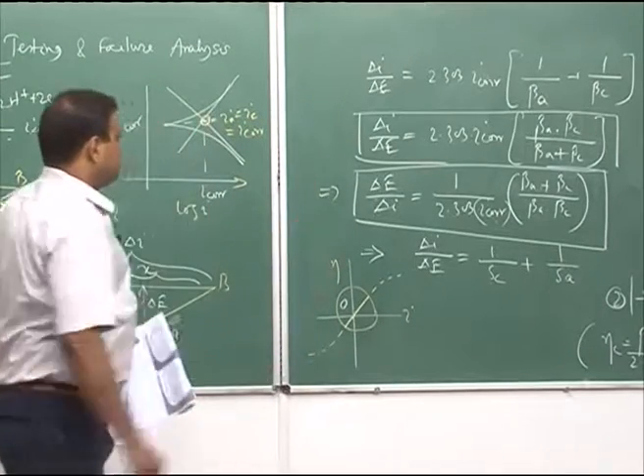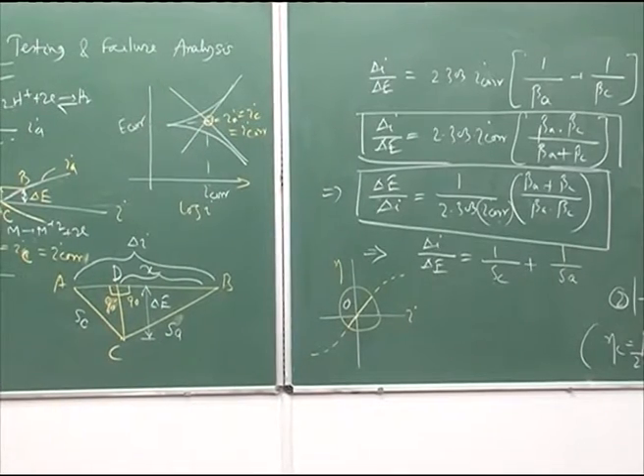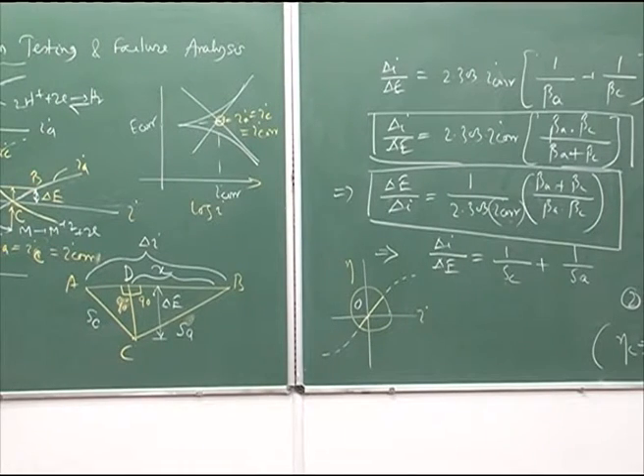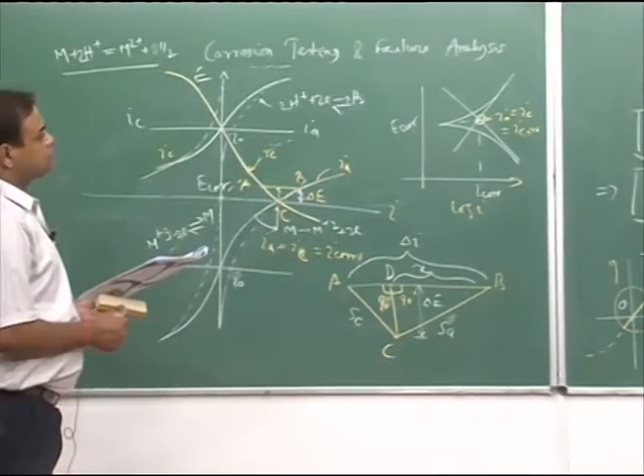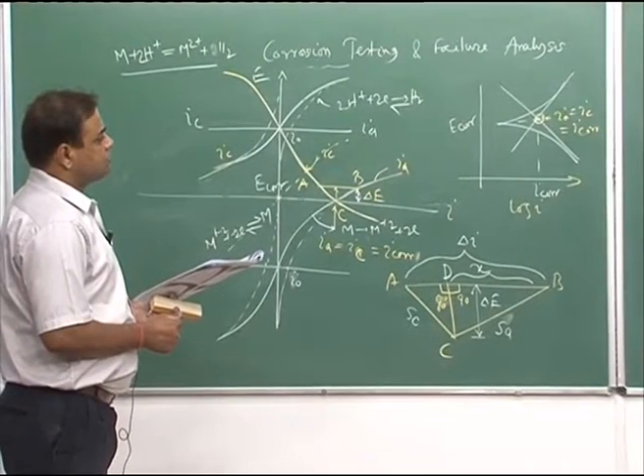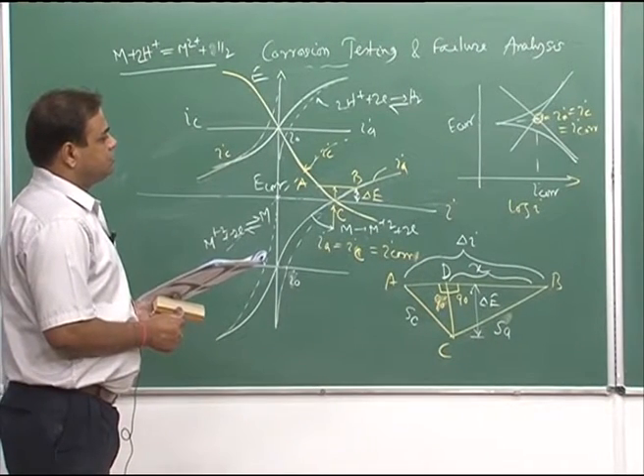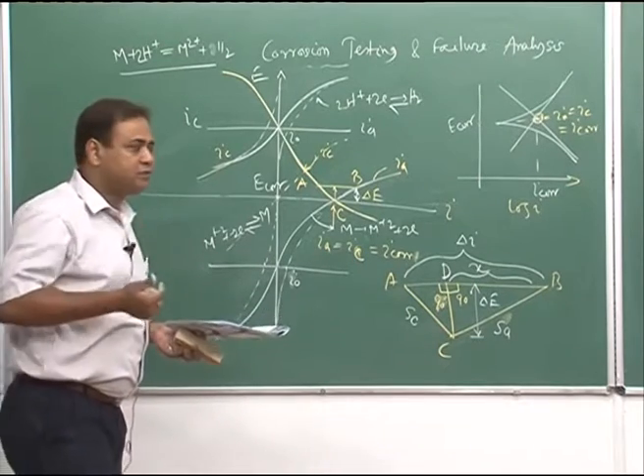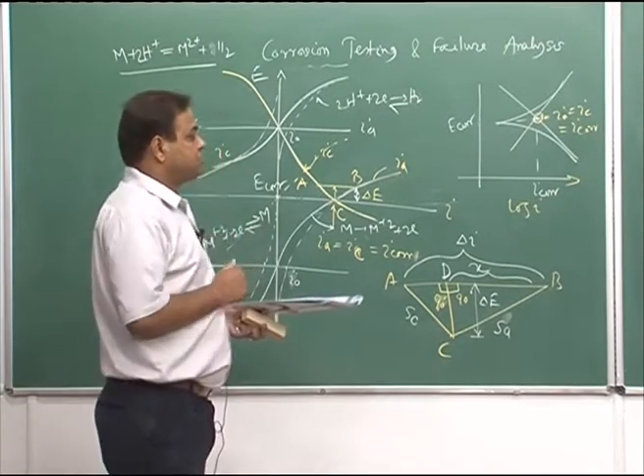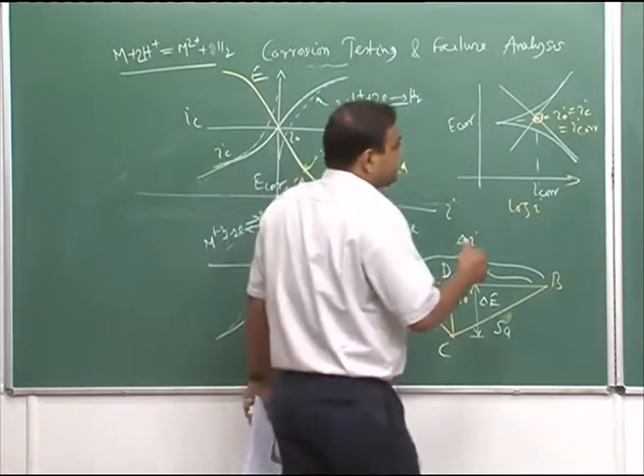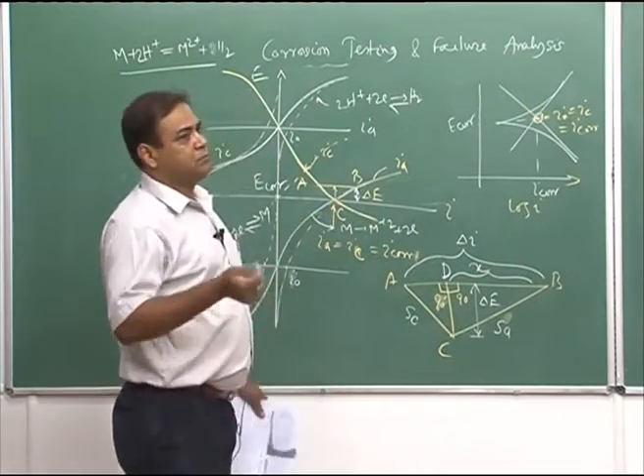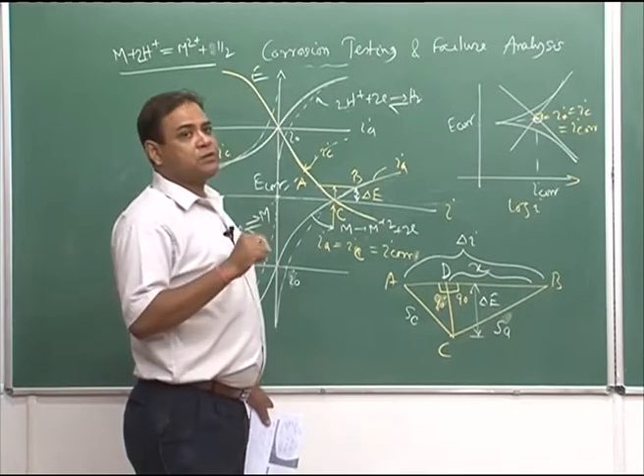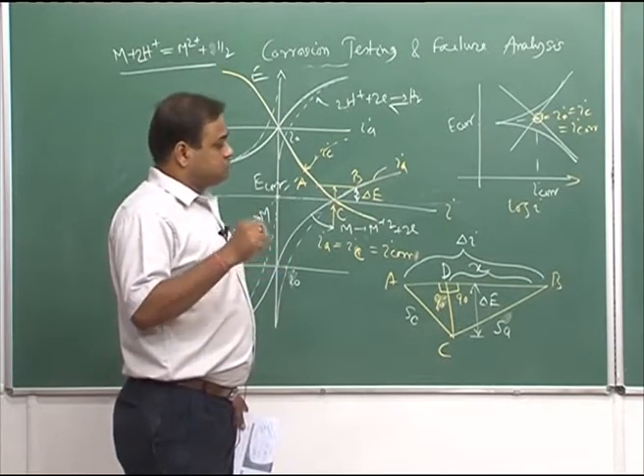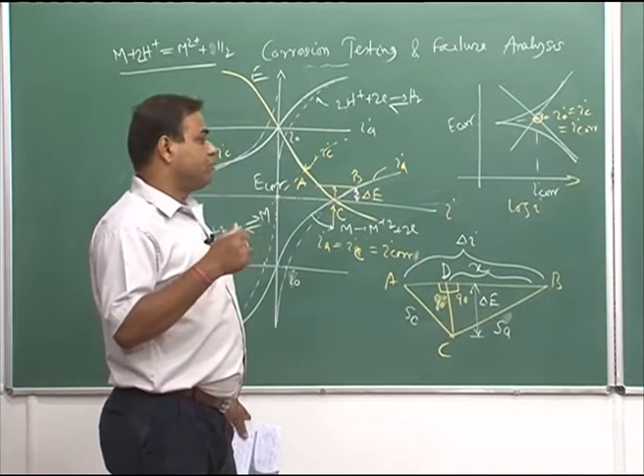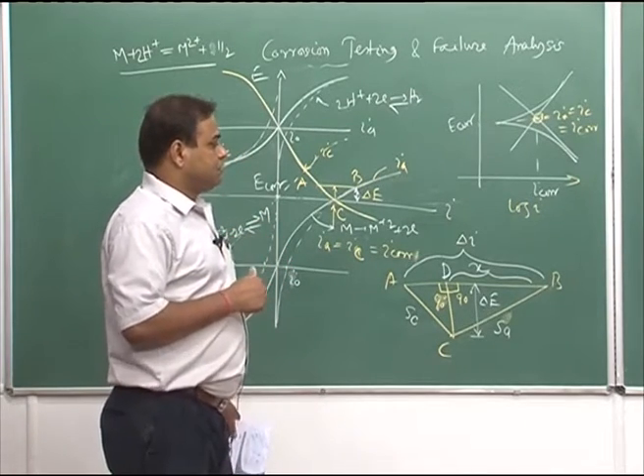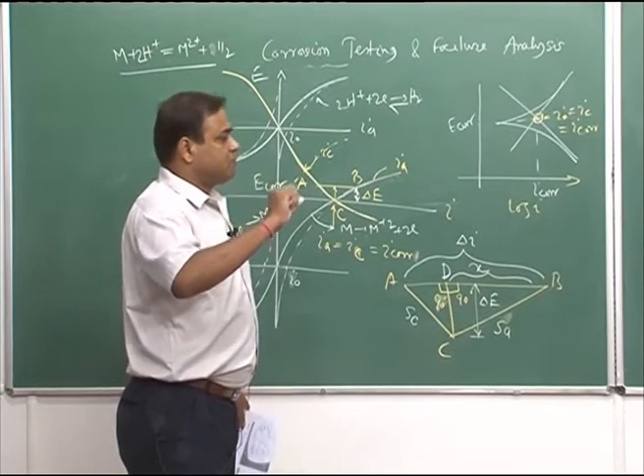So, this is overall the view of the principle of linear polarization, and this is advantageous over Tafel slope because here we do not go to a very high polarization. If we do not go to a very high polarization, we do not get any effect from resistance polarization, and we minimize the effect of concentration polarization, because we are operating in a very small over voltage.